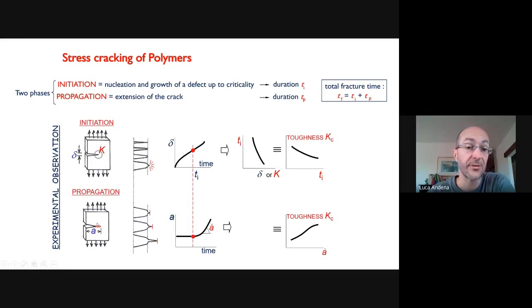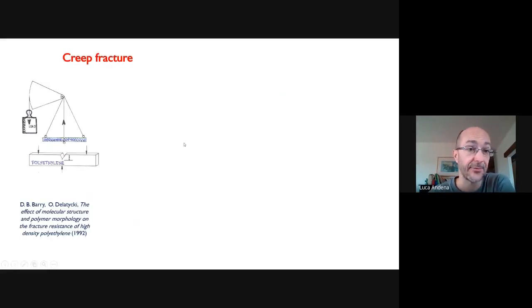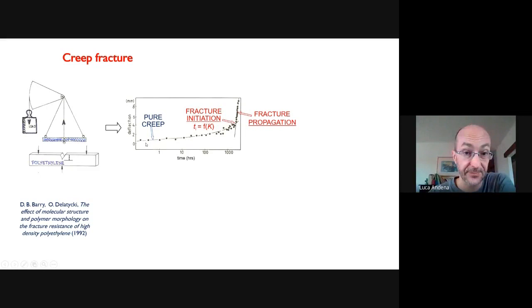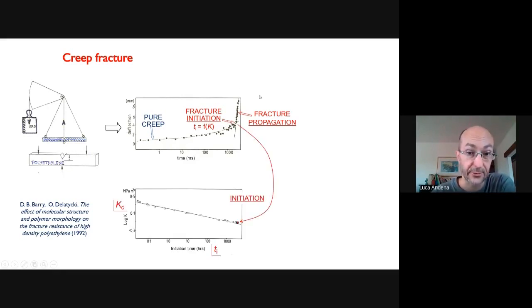And at the same time, once you have propagation, you establish a relationship between the applied K and the speed at which the crack will grow within the material. This is some example of data. Of course, the easiest loading case is one in which I apply a constant load, in this situation, to this notched bending specimen. And here you can identify the pure creep region in which the deflection increases because of creep, and then the sudden increase you have when you have fracture initiation.